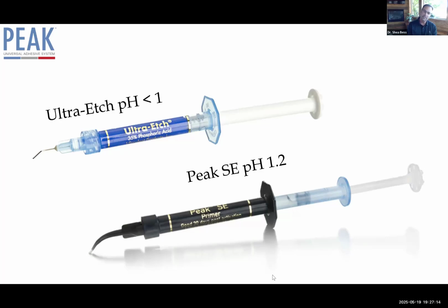Now, when you look at Peak SE, this is their self-etch. So you would use one or the other of these. And one of the things that you'll see with Peak SE is the pH is 1.2. Now, most SEs on the market are between 1.9 and 2.5 pH. And if you remember that pH scale is logarithmic, that will give you a sense of just how much more acidic that Peak SE primer is than many primers that are on the market. And by making it more acidic, you're going to solubilize that smear layer a lot better, which is going to increase your ability to get better adhesive bond strengths. And that's one of the reasons why Peak Universal Bond is so successful.